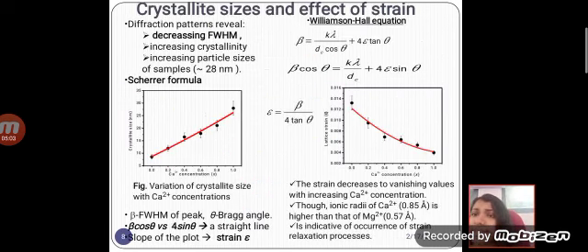And now the crystallite sizes were analyzed using the Scherrer formula. The decreasing full width at half maximum, which is indicative of increasing crystallinity, showed increasing particle sizes of up to 28 nanometers. Then the Williamson-Hall plot was used to analyze the strain developed in the samples.